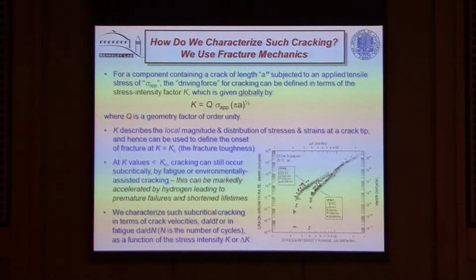And in the case of hydrogen, there are two primary factors that are important here. One is, of course, fatigue. Fatigue is always important. And hydrogen can accelerate fatigue, as I'll show you in a minute, in a variety of different ways. But in the presence of hydrogen, cracks can grow subcritically. You don't even need a cyclic load. They can simply grow under sustained or monotonic loading. And so we have to encompass both those phenomena.